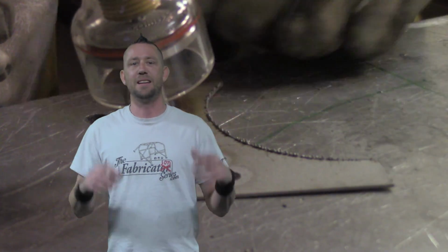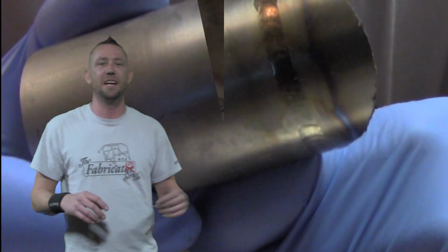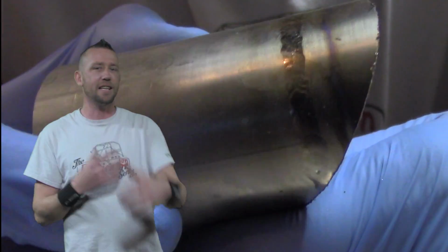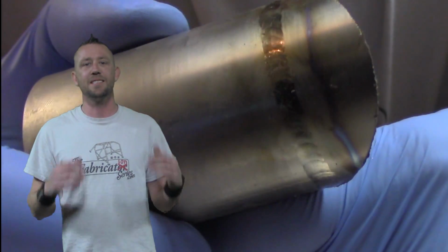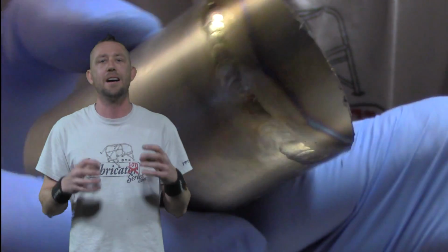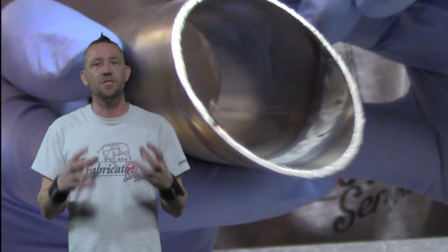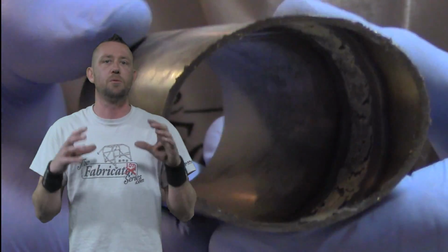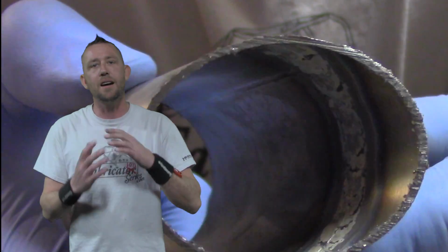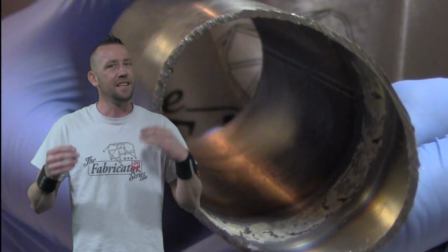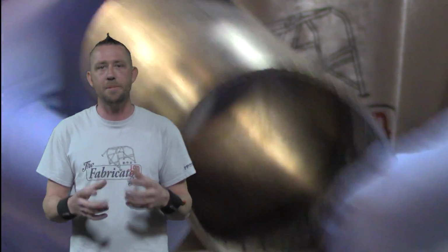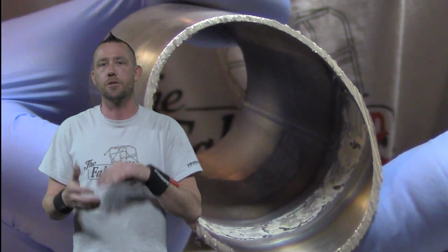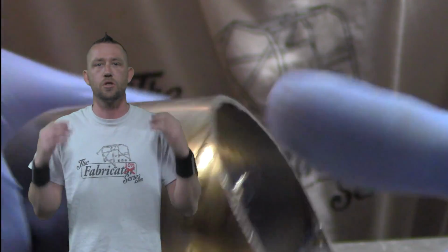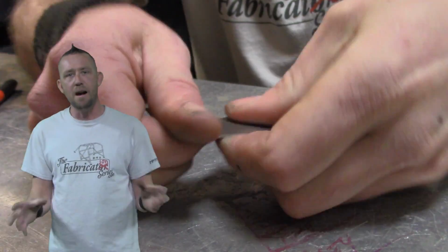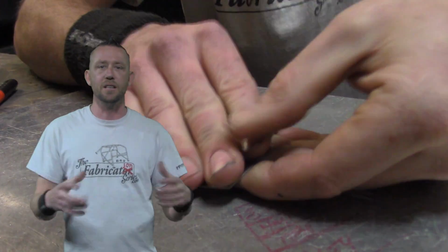You cannot get away with not shielding the backside of the weld as you weld it. If you look carefully at this piece, the outside looks like a good passing weld, but the inside is ridiculously oxidized. That happens so rapidly that it prevents the weld from penetrating through, because that oxide layer develops so quickly that even if you cook the everlasting crap out of it, it still won't puncture through. So you absolutely must shield your welds, as well as prepare them for a good solid weld.